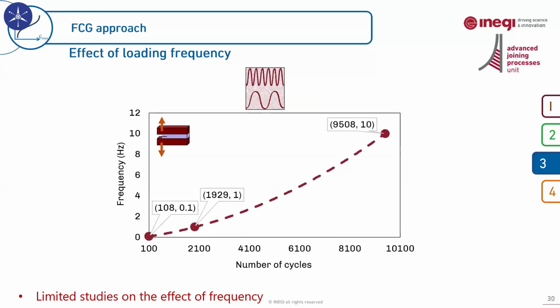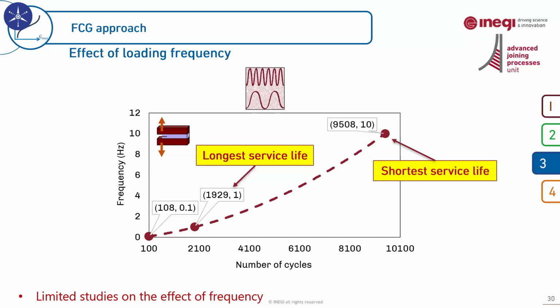Loading frequency is an important but relatively overlooked parameter in research. Fatigue life can be highly sensitive to loading frequency. And by increasing the loading frequency, the number of cycles at failure increases. While high frequency testing is sometimes used to make the testing time shorter, it can easily lead to misleading results and can overestimate or underestimate the service time. Here, for example, in our results, the longest service time occurred at 1 Hertz. And the shortest service time was for 10 Hertz. And when we analyze the adhesives under cyclic loading, and we change the frequency and make it different from real practice, we need to take into account all these important points.